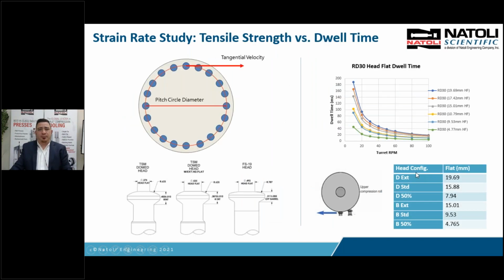Another way of looking at this is something called dwell time. And dwell time's been used for, I don't know, a century, where dwell time is a function of the head flat and the tangential velocity. So the larger the head flat, the higher the dwell time. So when that punch hits the roller, that punch comes down, it's consolidating. When it hits the head flat, it's no longer moving vertically, it's being held at a constant strain, and it's moving horizontally, being held under that head flat, that constant dwell in milliseconds. And again, that's influenced by the size of your head flat and the turret velocity.